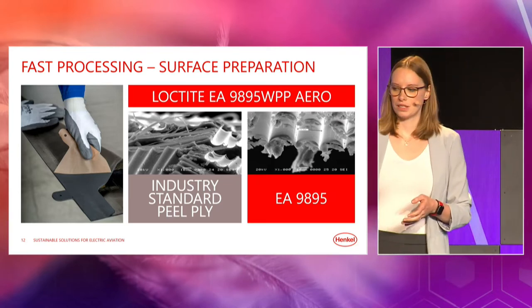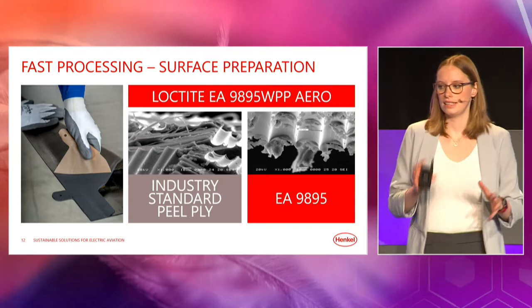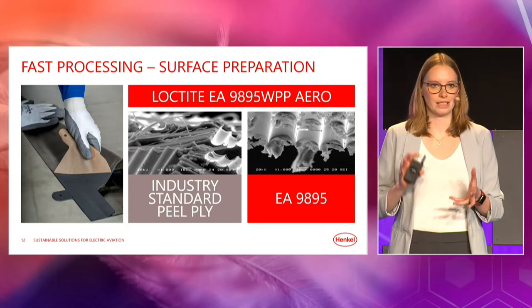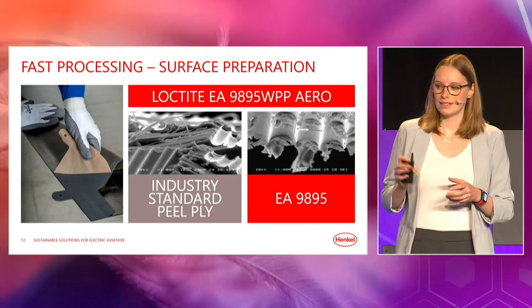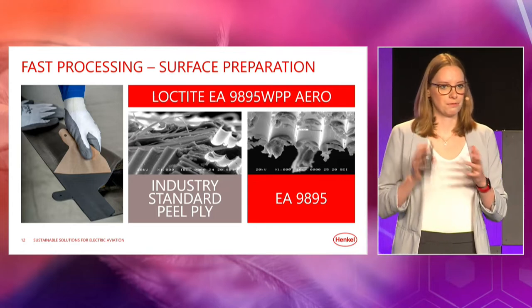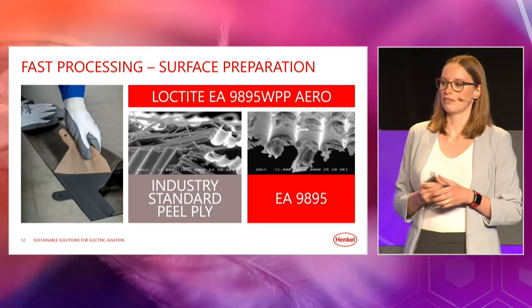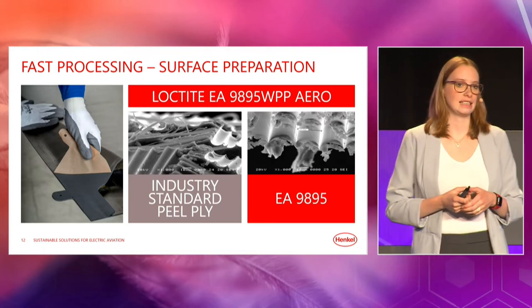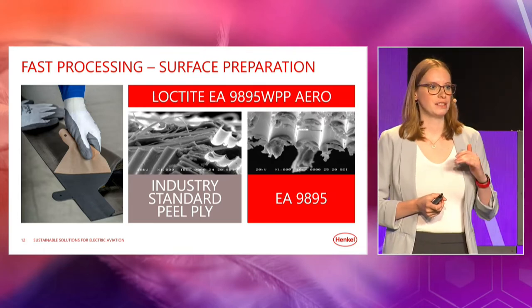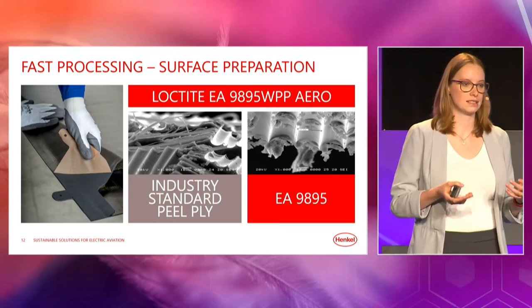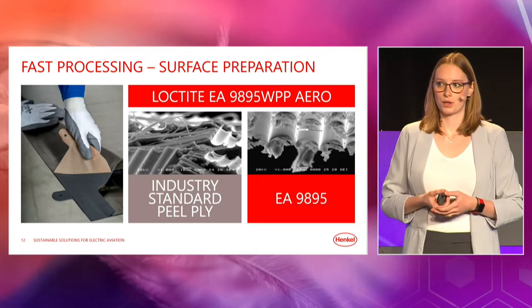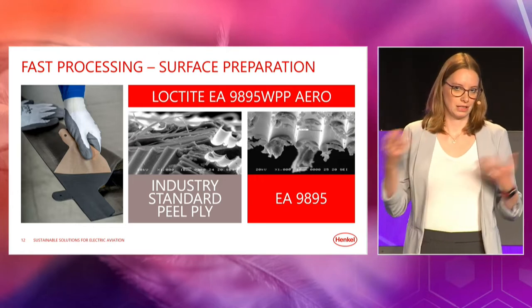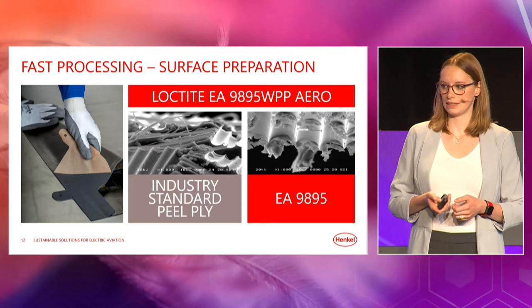As you can see in the pictures, the standard industry peel ply leaves the surface very mixed, and we have here and there some fibers. And on the right side, we have the EA9895, which leaves a very defined surface, and this is supporting the cohesive failure of the adhesive during testing.